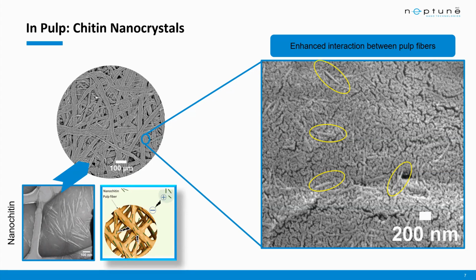And here is a SEM image that we took, and really look at the dispersion and the deposits of these individual chitin nanocrystals. They're deposited on a single strand of cellulose fiber. This image here is quite zoomed in, as you can see by the 200 nanometer scale bar. And we're clearly seeing the individually dispersed chitin nanocrystals within the structure. So we see good dispersion, which is typically challenging for nanomaterials, and we have good natural compatibility. So how does this really translate into performance?